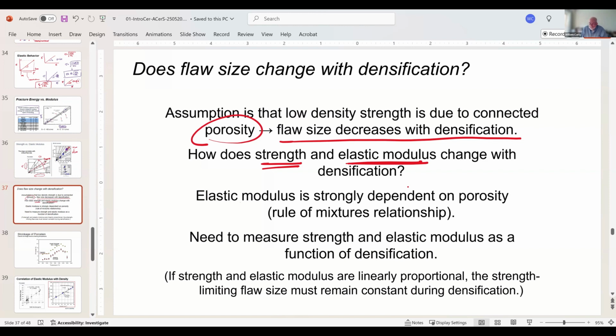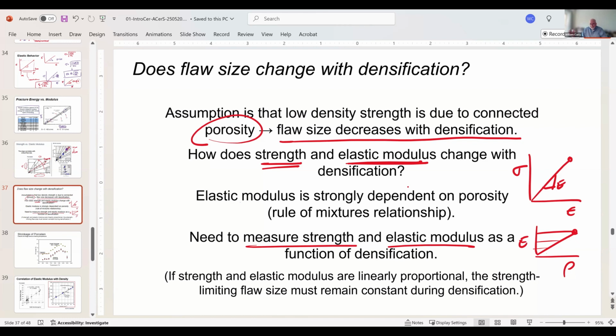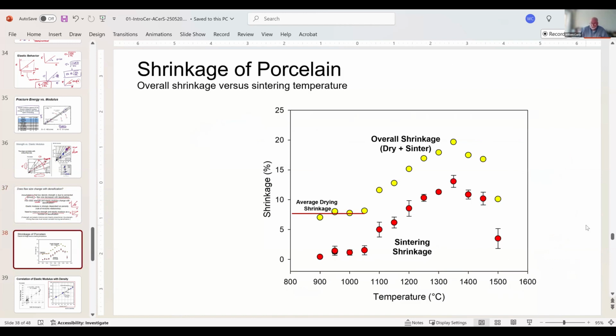If that happens, I shouldn't be using the elastic modulus which I had mentioned before. I have this relationship between strength and elastic modulus, but I shouldn't be using this elastic modulus value. It should be this one, rho versus elastic modulus. And when I'm at my peak density, I shouldn't be using that value. I should be measuring the elastic modulus as I go along in my system. So I need to measure the strength and the elastic modulus as a function of densification. If these are all linearly proportional, then the strength limiting defect is a constant during my system. That means my strength is dictated by the flaws intrinsic to the system when I started.